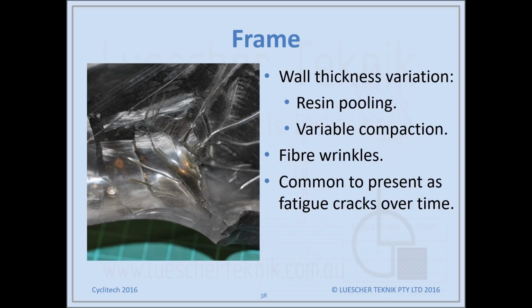Now here we have what you'd call a dog's breakfast. It's quite a mess. This is the head tube, down tube junction on an older bike, and you can see a lot of variation in wall thickness, and there's lots of resin pooling and variations in the compaction. There's fiber wrinkles. Now this is quite common in older bikes, and it was quite common to see cracks appear over time of use. Obviously at the root of a wrinkle, or due to the change in stiffness from the fiber variations and the resin pooling, cracks would appear in some of these older bikes.